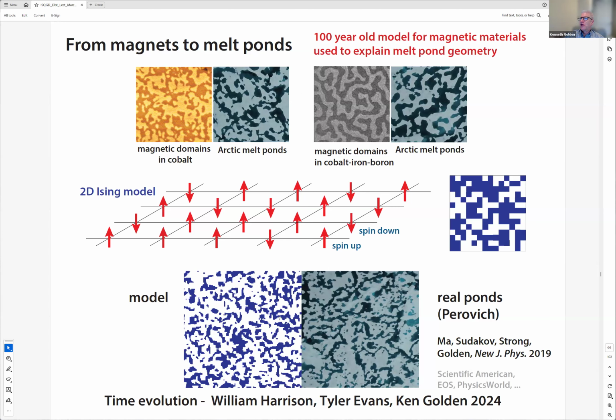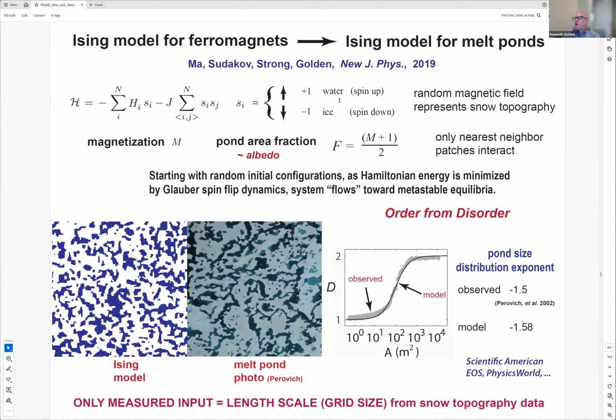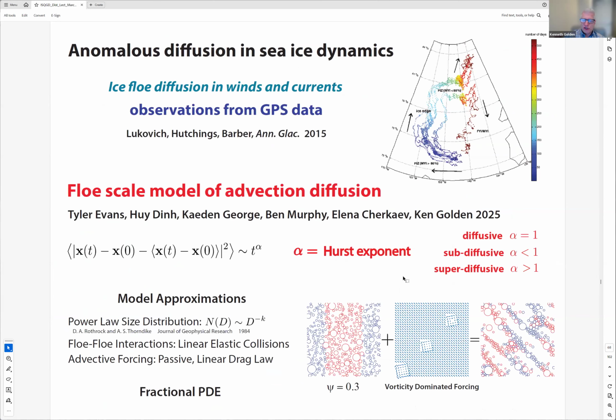And so we've developed this Ising model. Instead of spin up and spin down, we have water and ice, and then we start with random initial configurations. And then as the Hamiltonian energy is minimized by Glauber spin flip dynamics, the system flows towards these metastable equilibria. There's the Ising model. Here are our real melt ponds, and we can do an excellent job of predicting the fractal transition.